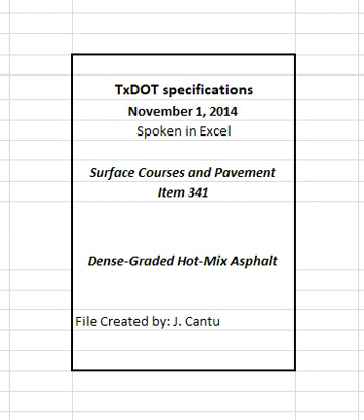Use fine aggregate, with the exception of field sand, from coarse aggregate sources that meet the requirements shown in Table 1 unless otherwise approved. Test the stockpile if 10% or more of the stockpile is retained on the number 4 sieve and verify that it meets the requirements in Table 1 for crushed face count, TEX 460A, and flat and elongated particles, TEX 280F. Table 1. Aggregate quality requirements. See table in specifications.